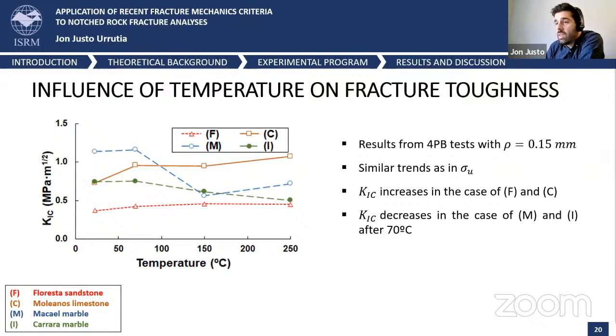Both the Floresta sandstone and the Moleanos limestone, those rocks with porosity, present an increase of the fracture toughness with temperature, while the two marbles present a decrease from 70 Celsius degrees onwards.